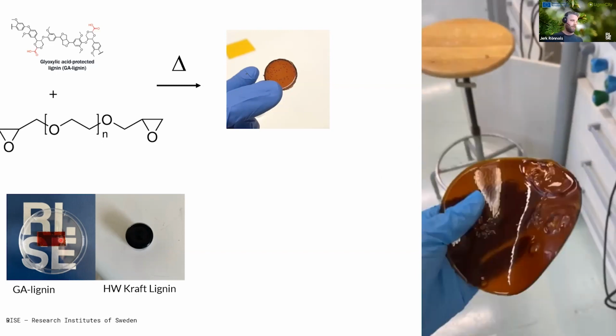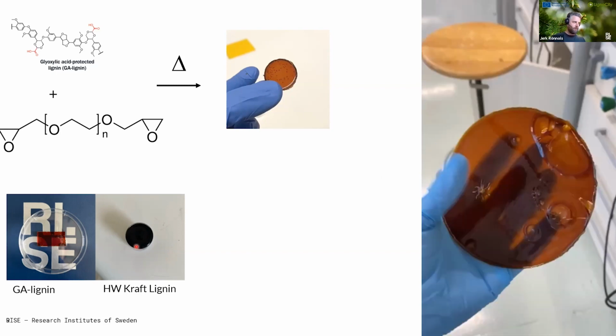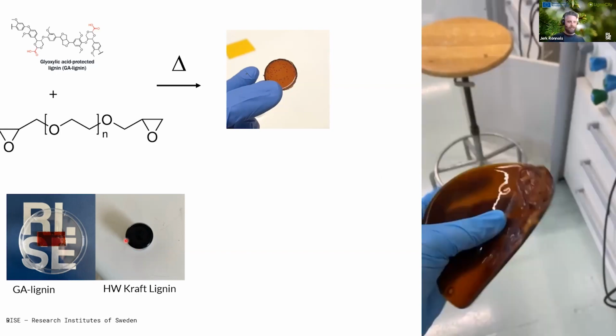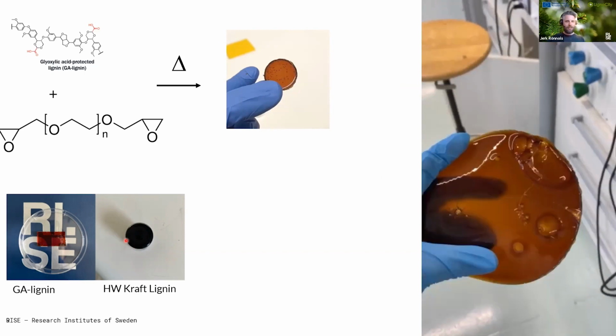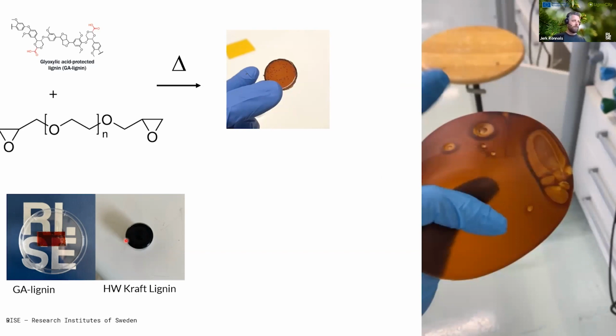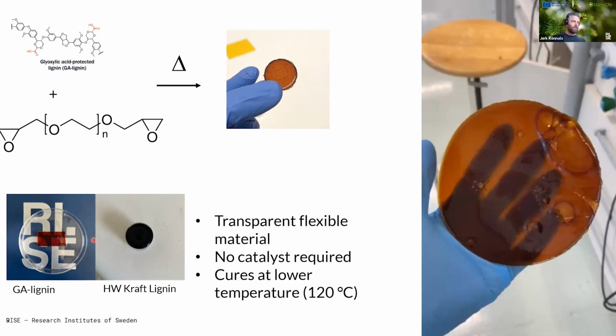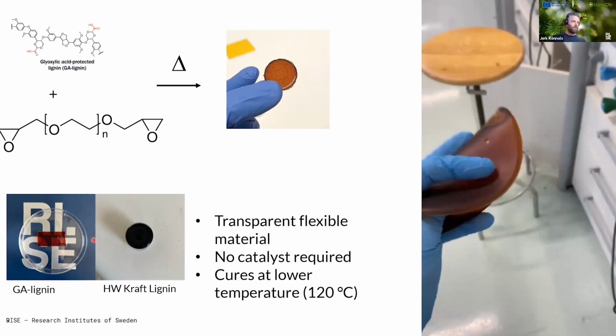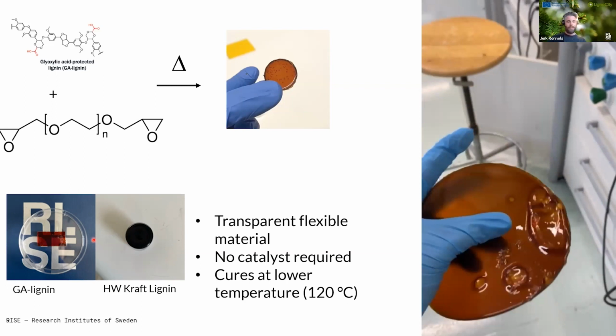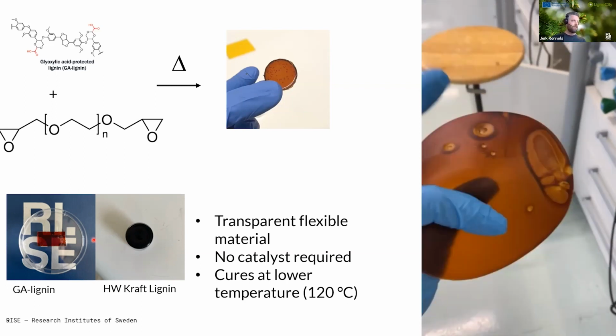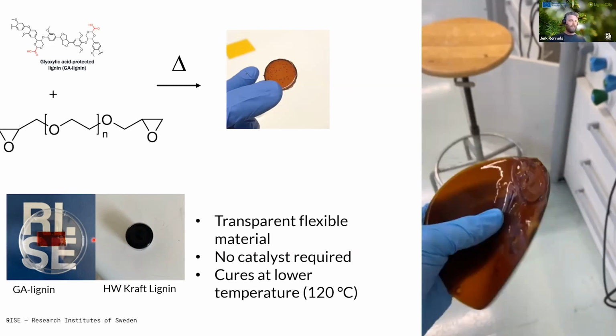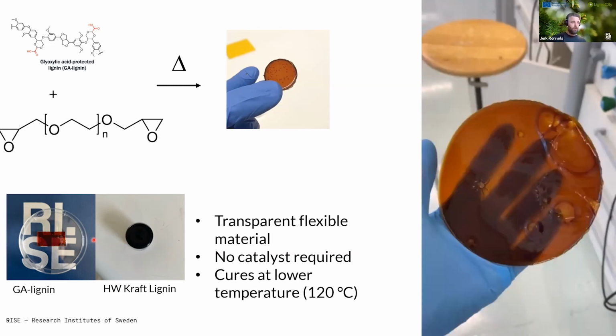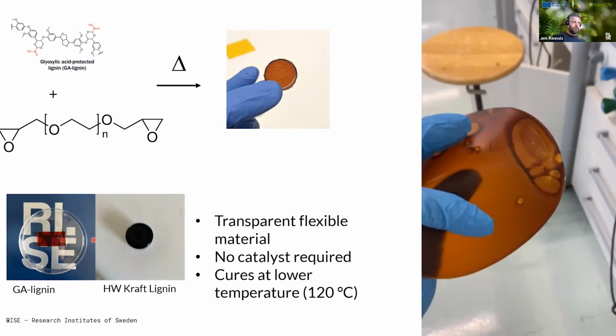And for reference, you can see what happens when we use kraft lignin instead. We get this black thing. You can't really see much more than that is a black circle, but it's black and opaque and very stiff compared to these other flexible ones. So very nice. Quickly, we could achieve a transparent, flexible material. As it turned out in the reaction, we didn't require a catalyst. The reaction occurred spontaneously between the lignin and the crosslinker. And we were also able to lower the curing temperature by 40 degrees to 120 degrees and still get an effective reaction.